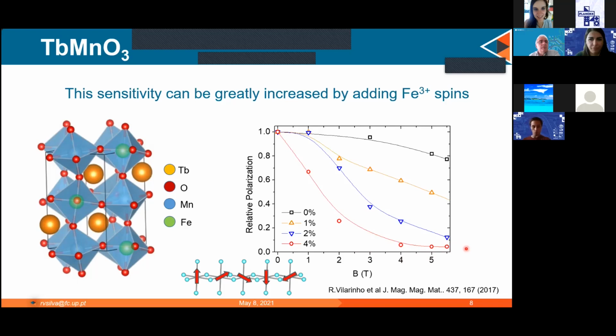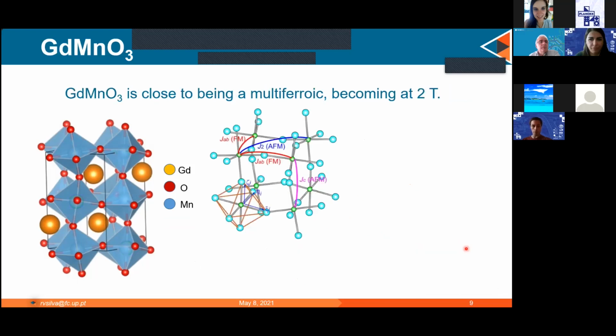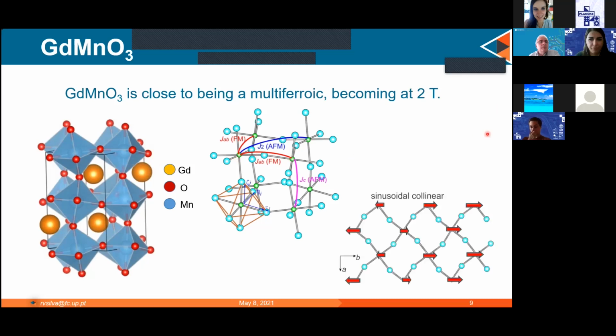Another way to explore magnetic materials and multiferroic materials is, for instance, using gadolinium manganite. So gadolinium manganite is like a parent of terbium manganite. It's very similar, but it's not multiferroic. It becomes multiferroic if you apply 2 Tesla of a magnetic field. And this is because gadolinium is larger, and these interactions between antiferromagnetic and ferromagnetic are a little bit different, in a way that you end up with this sinusoidal collinear magnetic phase, which does not break center of symmetry, so you don't have a ferroelectric polarization. Anyway, we can play with this material as well.